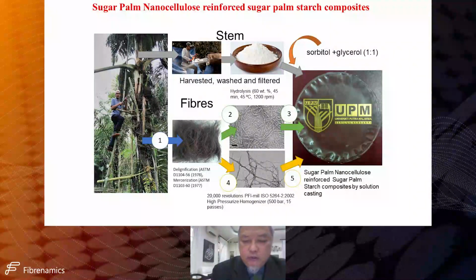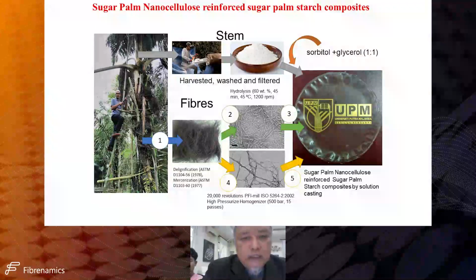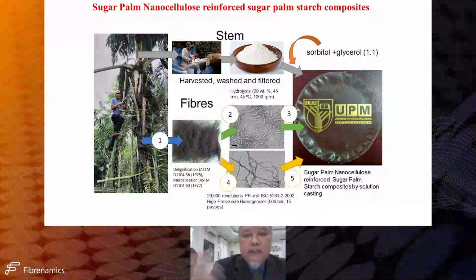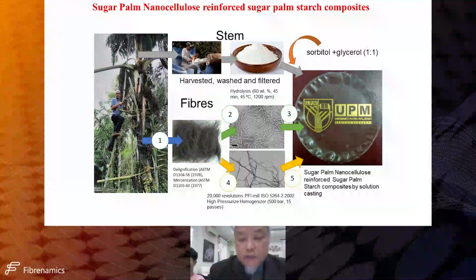And this is how the fiber, the nanocellulose, was produced. It's also how the starch was produced. It is quite not an easy job. We have to climb the tree and get the starch, and we do some processing to develop the fiber at the end. And using the right plasticizer, we got the nanocellulose biocomposite using the solution casting method.